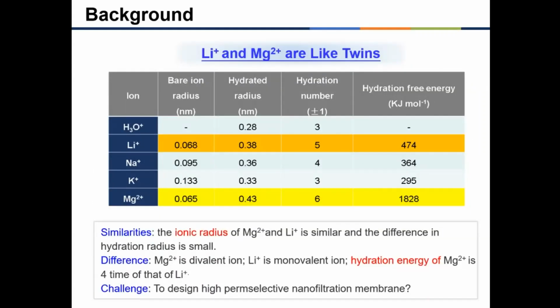The difficulty in separating magnesium-lithium ions is that the ionic radius of magnesium and lithium is similar, and the difference in hydration radius is small. But magnesium is a divalent and lithium is a monovalent ion. The hydration energy of magnesium is 4 times that of lithium. The challenge is how to design a high selectivity nanofiltration membrane.